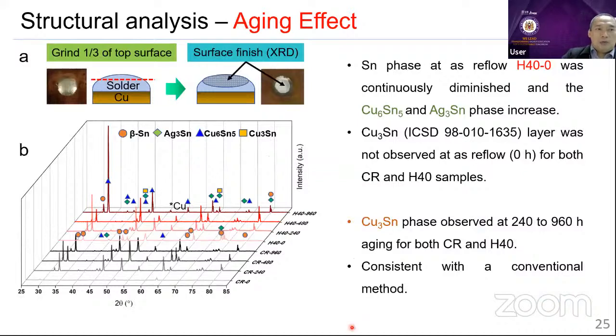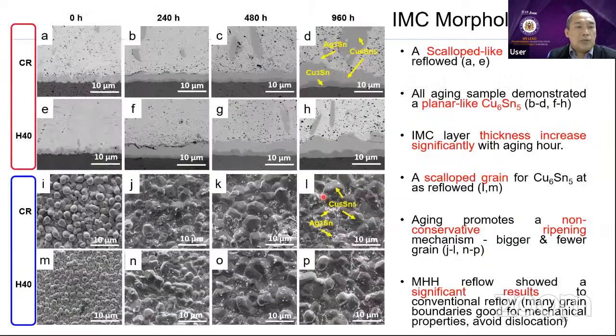Okay, again, we studied aging, and for sure with aging we can produce Cu6Sn5 and Cu3Sn. This one is the surface and cross-section morphology for the aging. She started with the microwave, and then we did the aging inside the oven. We cannot do the aging inside the microwave because it will take a very long time. If we run for a longer time, sometimes it's very dangerous.